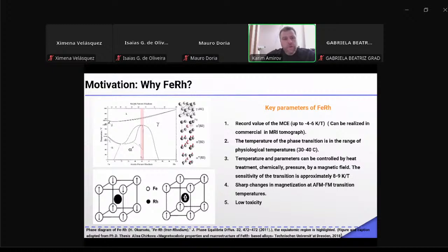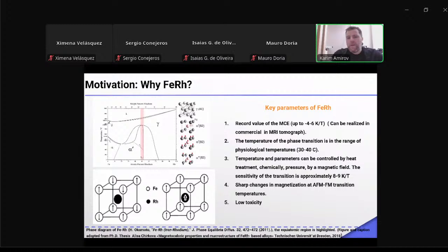So, why is iron rhodium interesting? First, it has record values of magnetocaloric effect, between 4 and 6 Kelvin per Tesla, available in a commercial MRI tomograph. The second point is the phase transition temperature, which is close to physiological temperature, between 30 and 40 Celsius. The third key point is that these parameters can be controlled by heat treatment, annealing, pressure, and magnetic field.